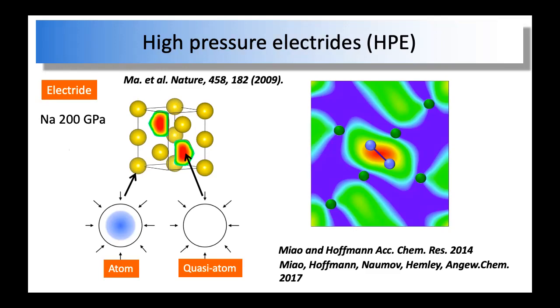The DFT gap is about 1.4 eV, right? And then the DFT calculations show clearly the reason. The reason is simple. From the DFT theory, the sodium suddenly takes a structure that has open sites, and these large empty sites can accommodate the electrons, and two electrons will occupy one site, and it plays the role of an anion, like sulfur and oxygen taking two electrons. So therefore, the sodium becomes an insulator because it's as if it becomes a compound, right?